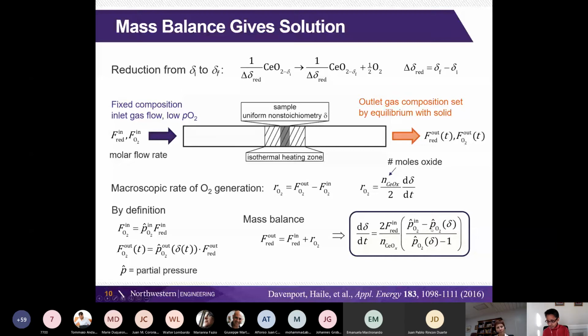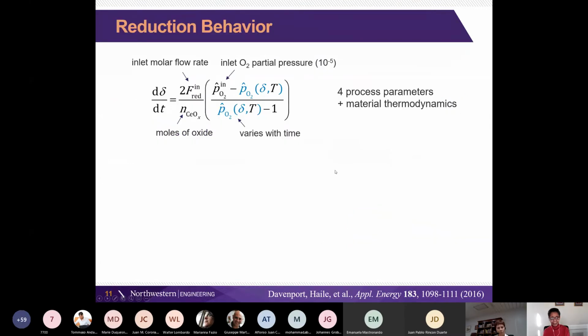And this oxygen partial pressure is a function of non-stoichiometry. That is our thermodynamic measurement. So everything is predictable here. We have a very, very simple set of assumptions. We need to make sure that our assumptions would be valid for our actual experiment. But if they are valid, then this is a very simple way to calculate the oxygen release. And we can do something analogous for oxidation, accounting for thermolysis. I may or may not go through that, depending how quickly I'm speaking.